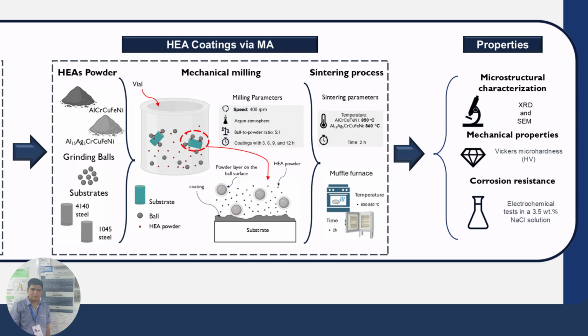Finally, to ensure proper densification, structural stability, and a strong metallurgical bonding with the substrate, the developed coatings underwent a vital post-deposition sintering thermal treatment. Afterwards, the functional properties of these sintered coatings were thoroughly characterized using X-ray diffraction, scanning electron microscopy, micro-hardness testing, and electrochemical corrosion assays.